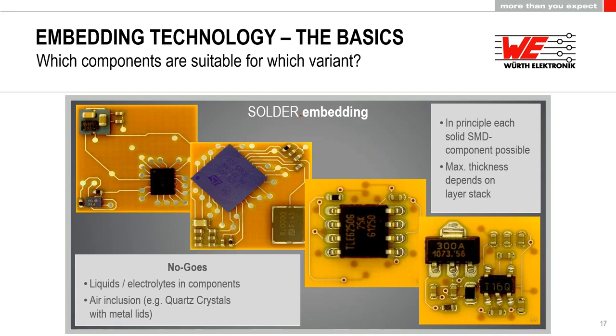Another thing is air inclusions or air cavities inside of the components. This is critical as well, because during lamination, in the first step, there is no mechanical stress onto the component because the component sits inside this cavity, as I've shown in the previous slides. But when the resin is completely flowing around the component, there will be some kind of pressure onto the component as well. So if you have a cavity inside the component, for example, like a quartz crystal with a metal lid, this pressure might bend this metal lid to the inside, and either the functionality of the component is not what you're used to, or it will be completely destroyed. So we'll have to take a look at this.